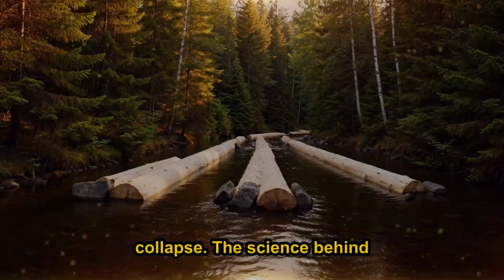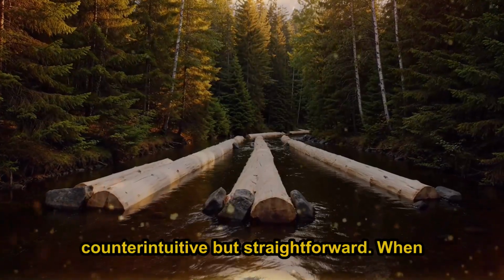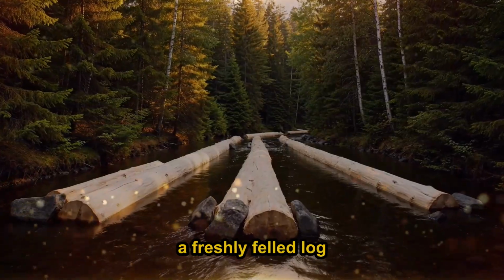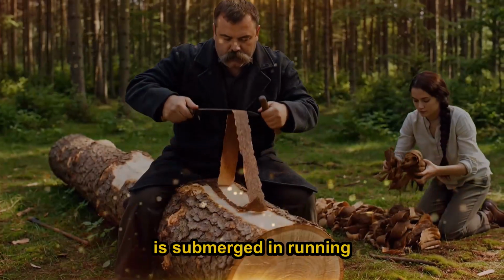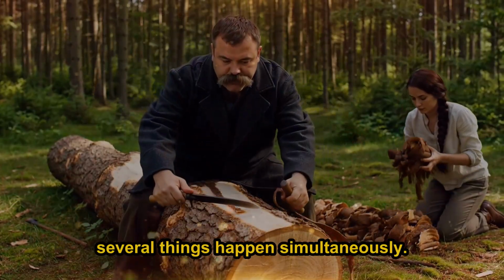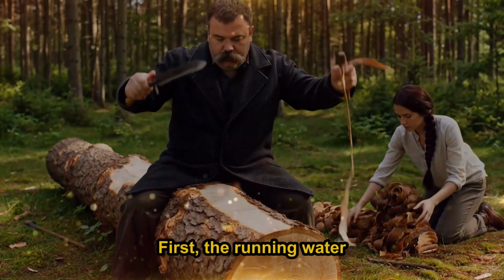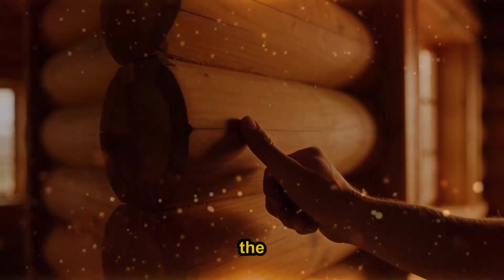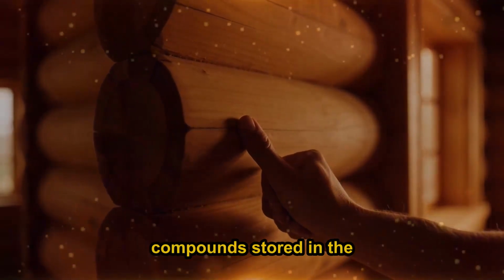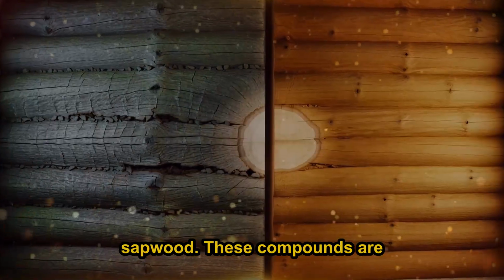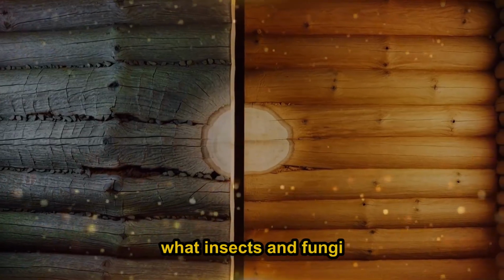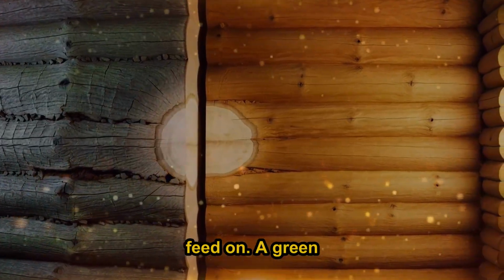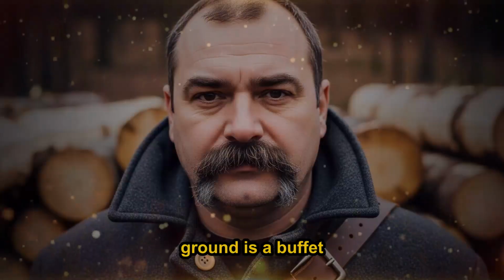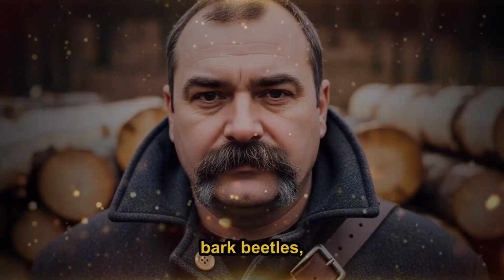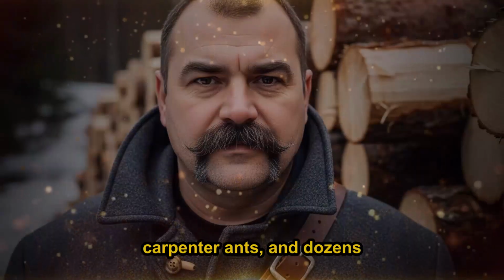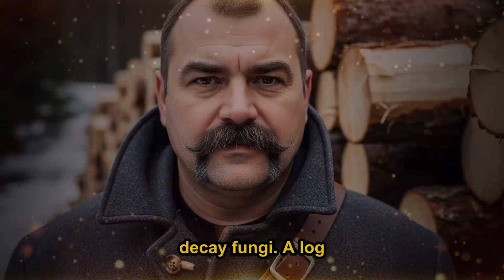The science behind water curing is counterintuitive but straightforward. When a freshly felled log is submerged in running water, several things happen simultaneously. First, the running water dissolves and carries away the sugars, starches, and sap compounds stored in the sapwood. These compounds are what insects and fungi feed on. A green log sitting on the ground is a buffet for powder post beetles, bark beetles, carpenter ants, and dozens of species of wood decay fungi.